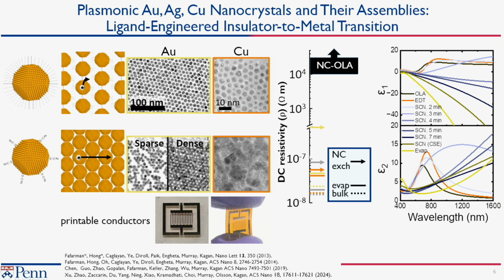One of the things that we were interested in at the time that we actually started looking at the characteristics of these particle systems was their optical characteristics. And so if you think about a system that looks like this, where again, it looks like an insulator, very highly resistive at DC. At optical frequencies, it also looks like an insulator. If this is the real and imaginary parts of the dielectric function, if you look at the black curve here, you see that it's everywhere positive, consistent with it being a dielectric and insulating material, even at optical frequencies.